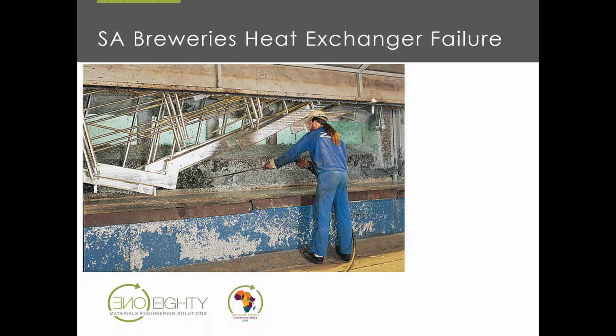So when the item is galvanized, it goes to the galvanizer, it stands outside for a couple of days, has no corrosion protection on it. That's all right. Rust a little bit. That's also all right. It's then placed into an acid bath, where the acid cleans off the rust and creates a nice substrate onto which the zinc then bonds.